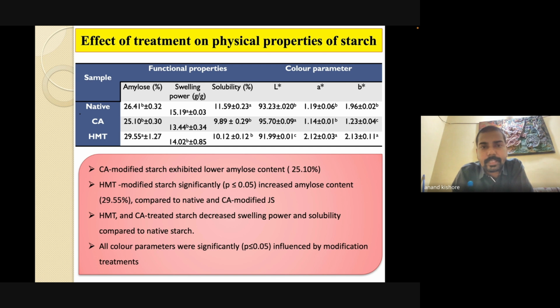Amylose plays a crucial role in the starch properties because it affects the film forming ability. After modification, we found that HMT has a higher amylose content. After the heat treatment, there may be breakage of the amylopectin and leaching of the amylose, so this value is very high. But in the case of citric acid, the value is less compared with the native starch, because when we apply citric acid, we have cross-linking. It strengthens the amylose and reduces the leakage of amylose through the structure. That may be the reason behind the reduction in amylose content.